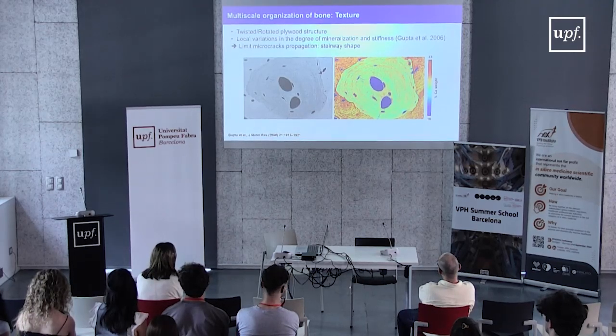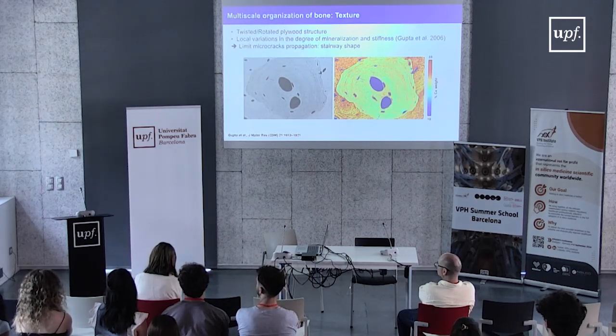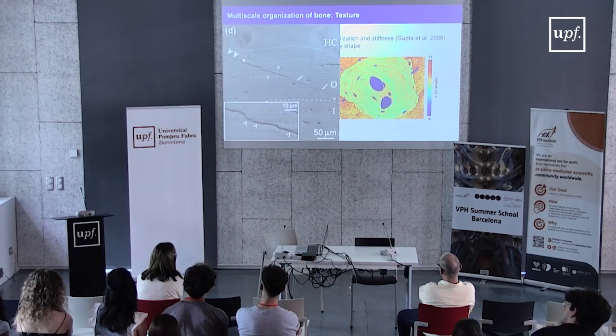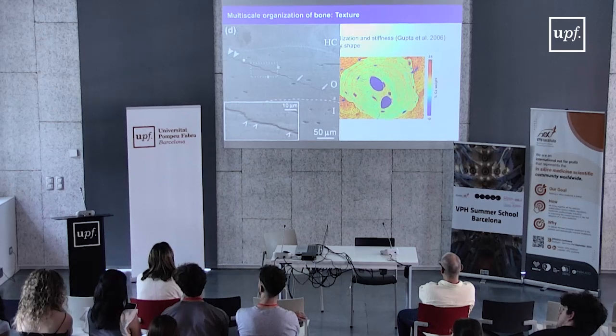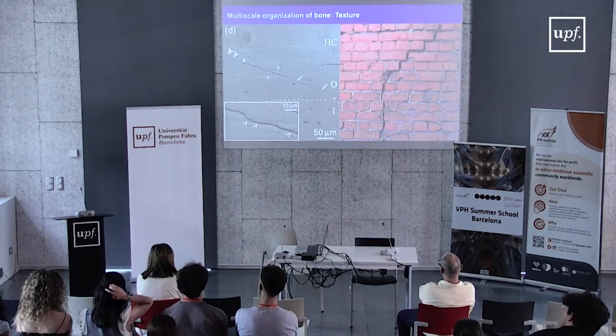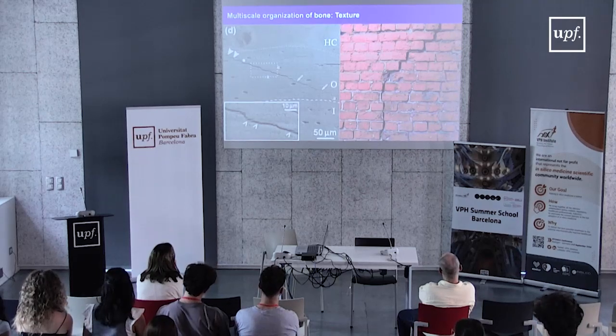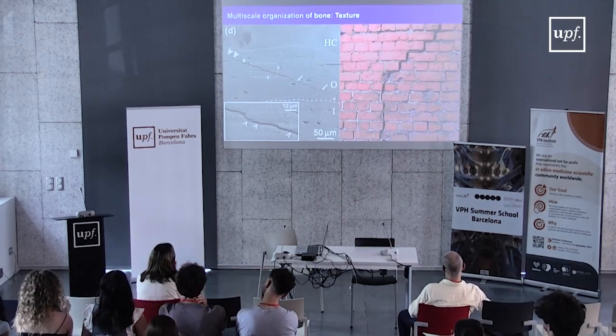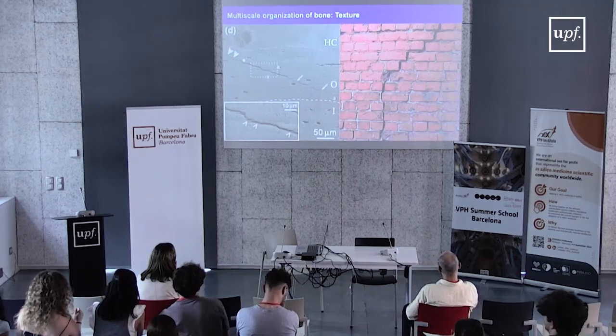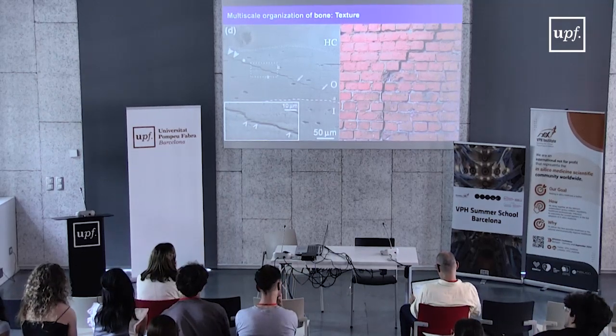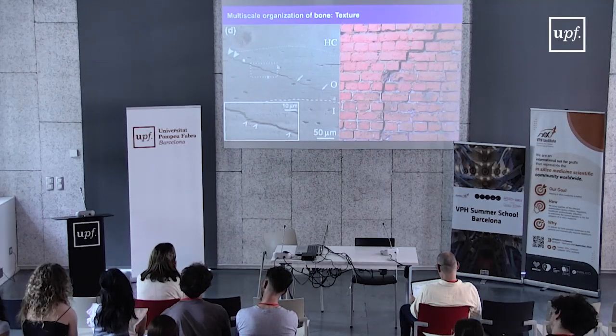And this pattern is also important to counter the development of microcracks inside the bone and to propagate these microcracks into a stairway shape. You can see here, if we had a material that was uniform, the cracks would propagate quite massively in one direction. By alternating this pattern with zones of high mineralization and low mineralization, we can make really a stairway. It's exactly similar to what happens in a fracture of a brick wall. If you have compressive strength applied to the wall, you will have these stairway cracks. So this is another adaptation of the bone to resist fracture.